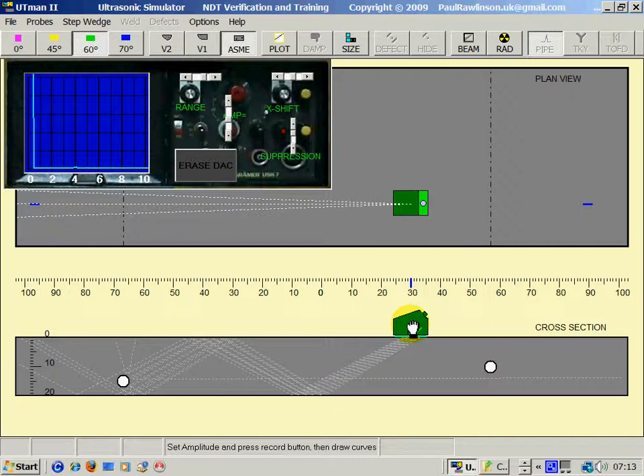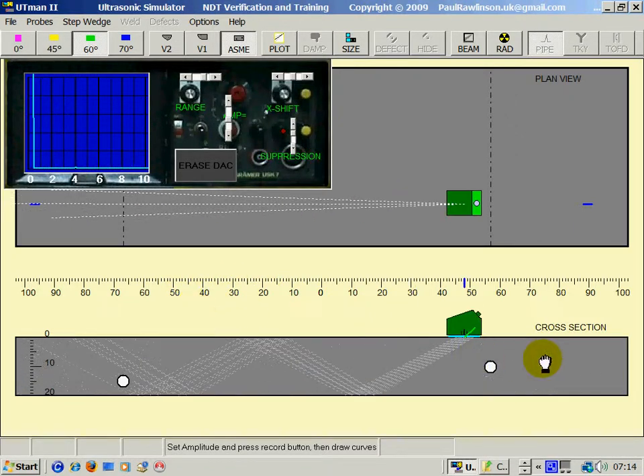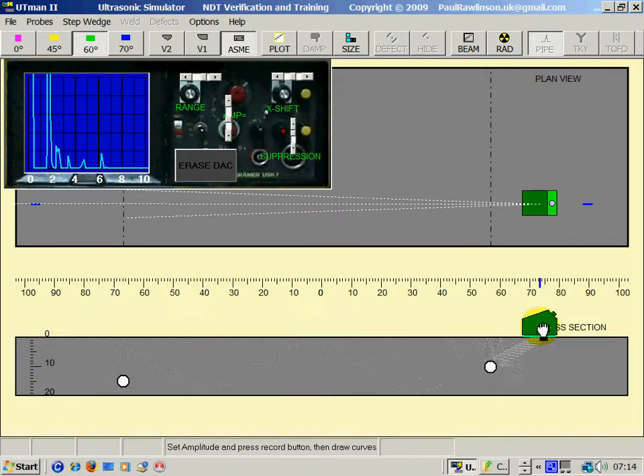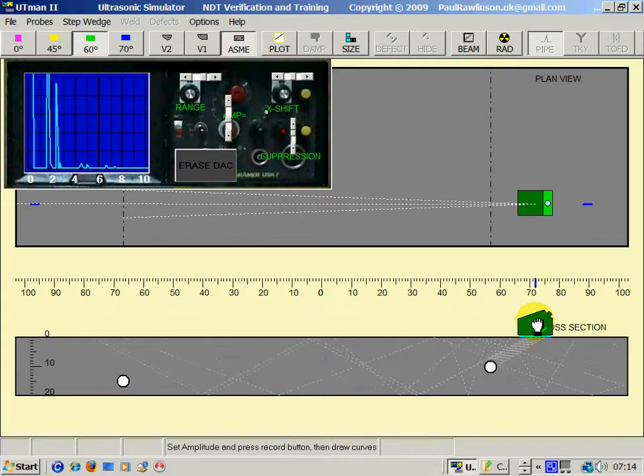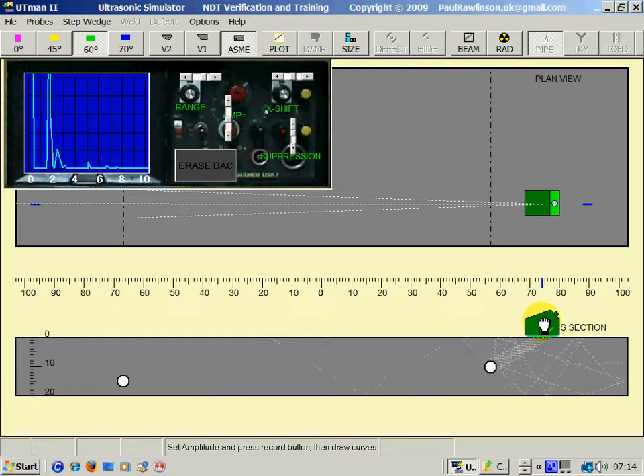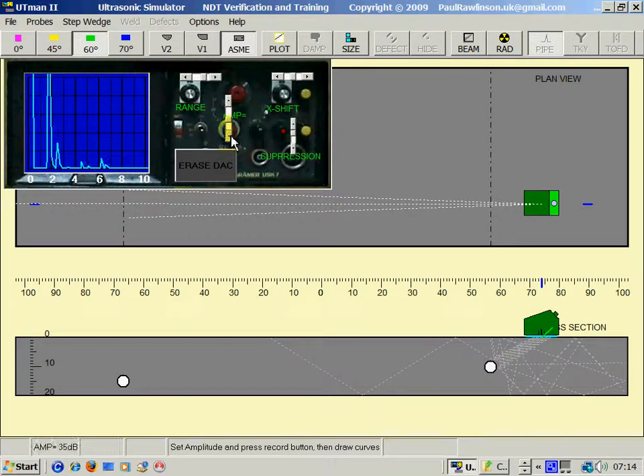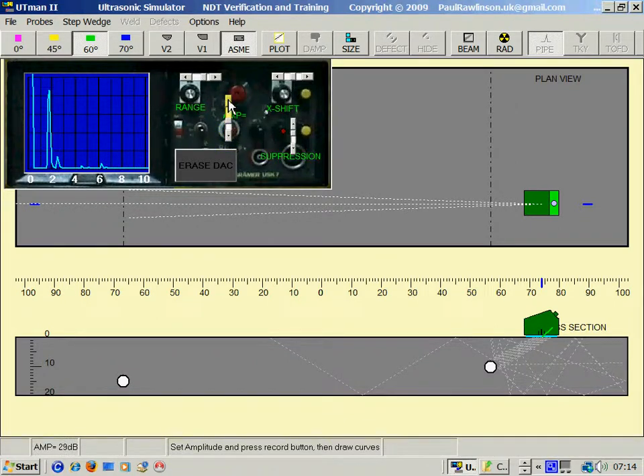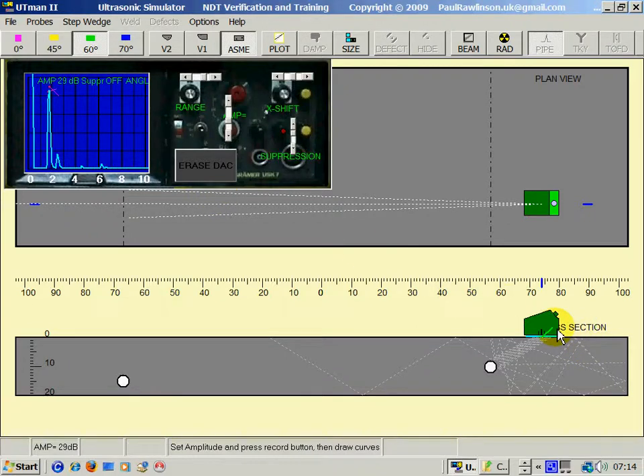Just like a real echo, it will diminish by distance. So as you get close to a defect, like this hole here, this flat part of this through drilled hole, you reduce the amplitude to about 80%, and then mark the top of it with an X.